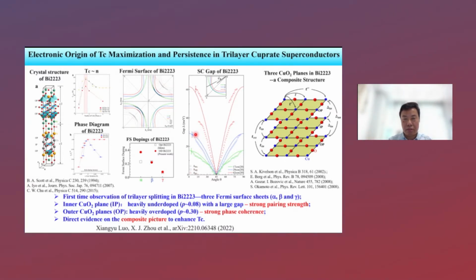measured the superconducting gap on the Fermi surface sheets. And in this case, we have really provided direct evidence for the composite picture proposed a long time ago by Steve Kivelson. In this case, because we have three layers of CuO2 planes, the inner one is heavily underdoped. The doping is about 8%, but it has a larger superconducting gap, about 60 millivolts. So it acts like a strong pairing strength source. On the other hand, the outer two planes are heavily overdoped, about 30%. Actually, it shouldn't be superconducting.